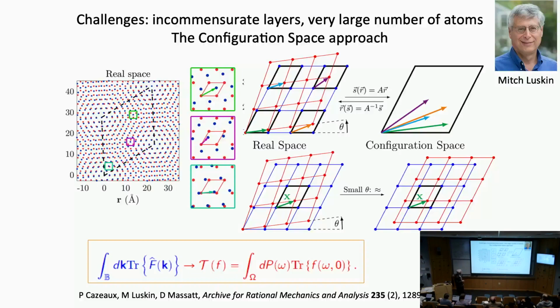And you can generate in real space all these possible local environments by simply taking one layer and displacing it with respect to the other layer. And by doing so, you reproduce all the local configurations, at least for small enough angles. This allows us to change integrations over momentum space, which is the standard way of doing these kinds of calculations in condensed matter physics, to integrals over configuration space. Capital omega is the set of all possible local configurations, and little omega labels those configurations.